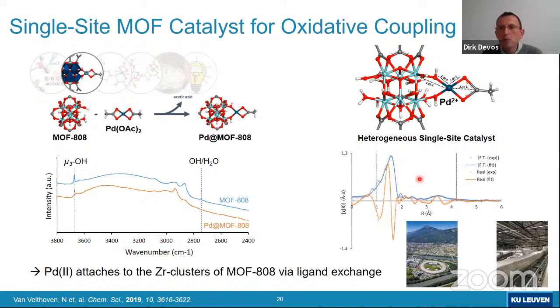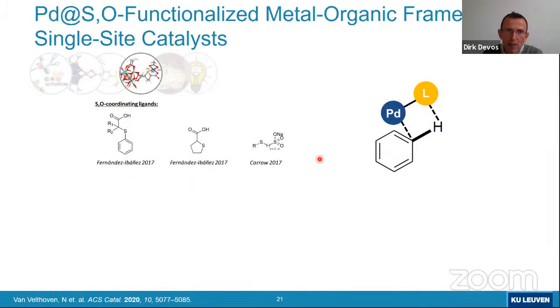And the precise binding mode of palladium on the cluster, we actually also documented in more detail by XAS measurements. And then the overall picture that emerges from that, without going into all these spectroscopy details, is that indeed the palladium is sitting one by one on this zirconium cluster of the MOF. And that's how the MOF stabilizes the palladium's activity eventually. Okay, so you see that even just palladium on the pure MOF without any other modification is already giving some important advantages, stabilizes the palladium in its oxidation catalysis activity.